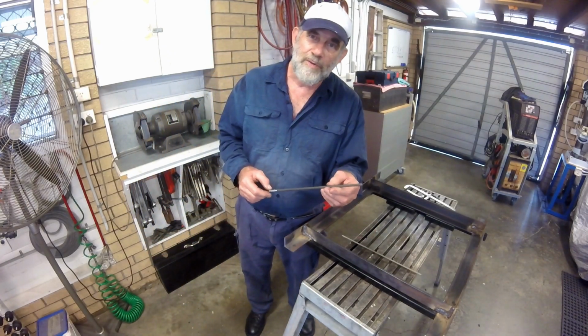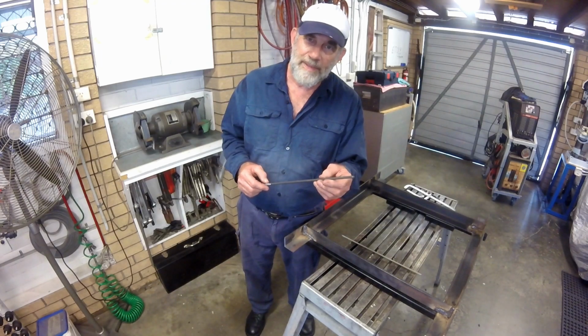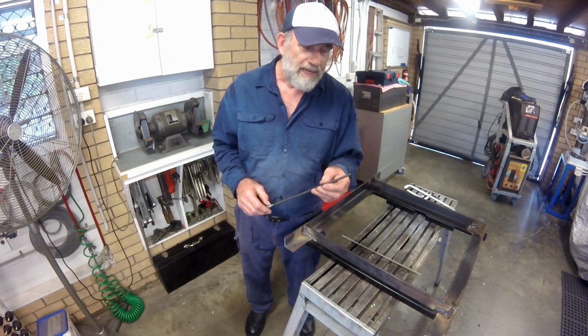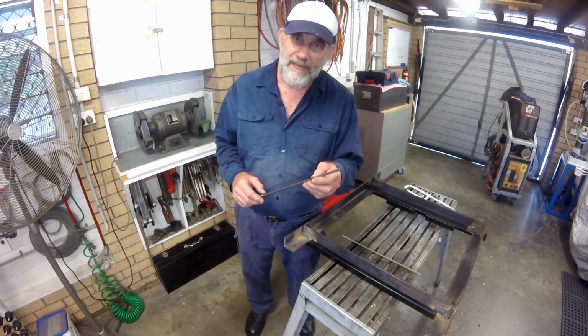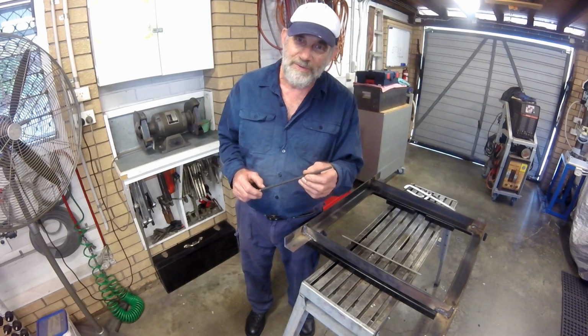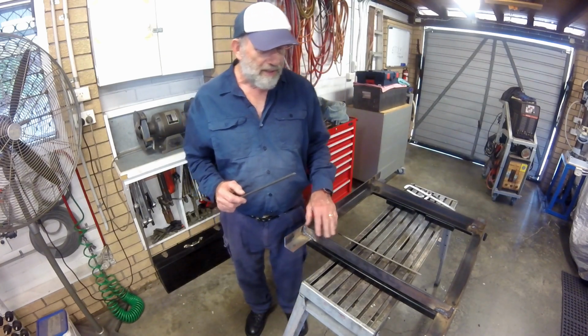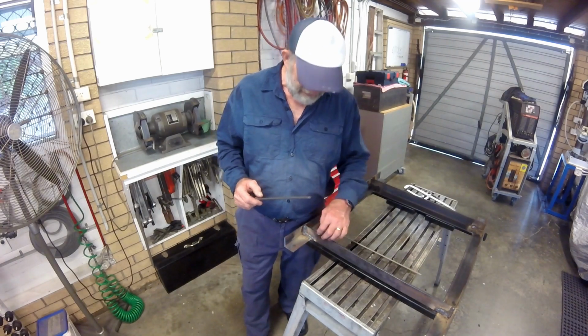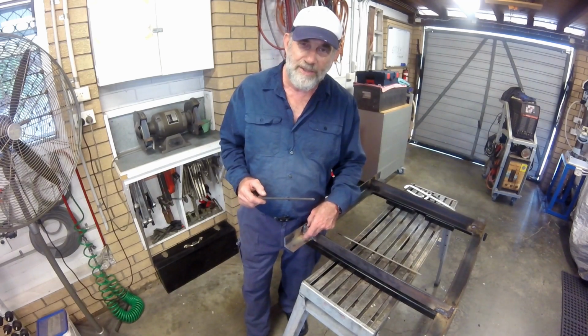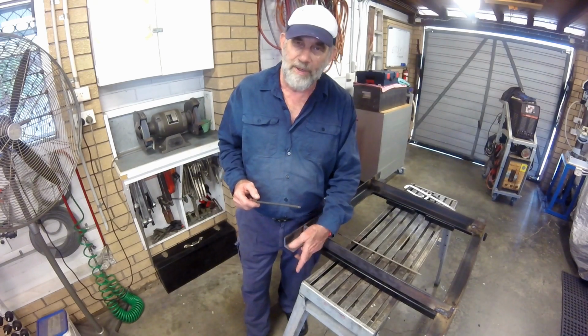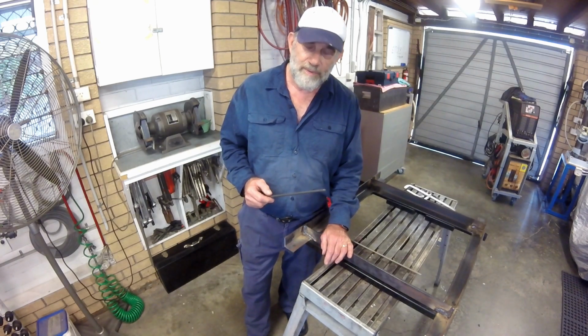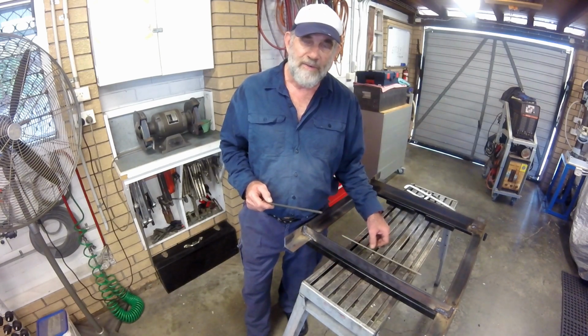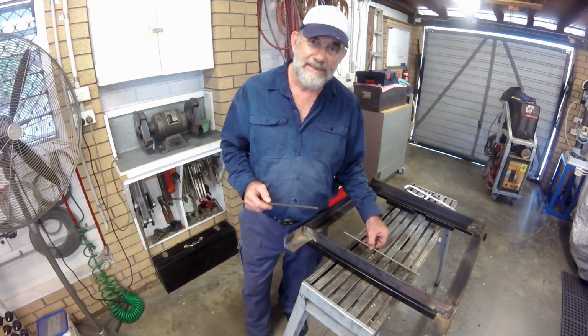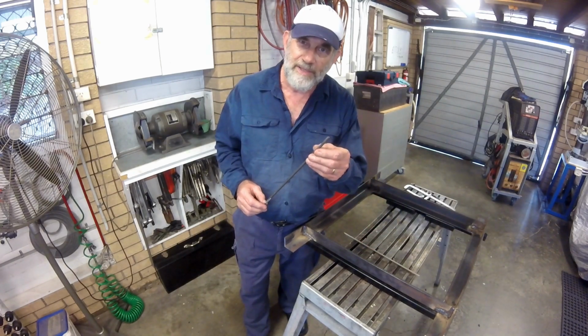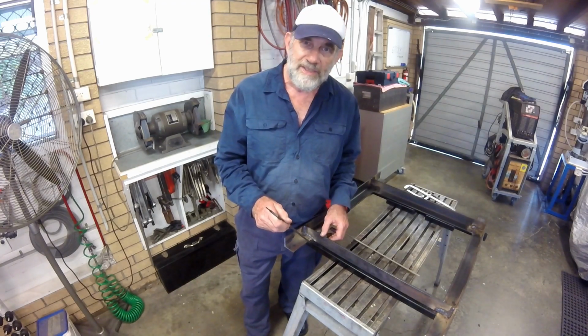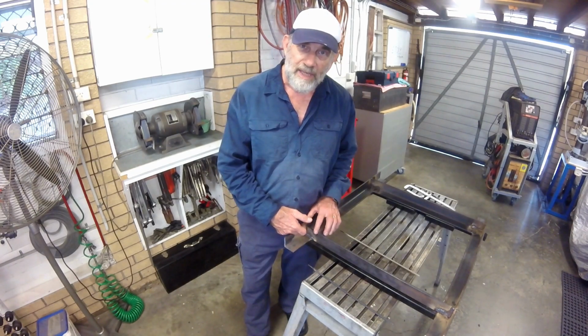The beauty of the 7024 is that you can weld quite rapidly with it, and that's good. And also, when you have a gap, it fills it very readily. One of the problems I had when I cut out the joints here is that I provided too much clearance to the bottom angle, and I was left with some reasonable gaps. So rather than waste it on 7018, I got out some 7024s. Easily fills the gap. For the other joints, it was a good fit up.